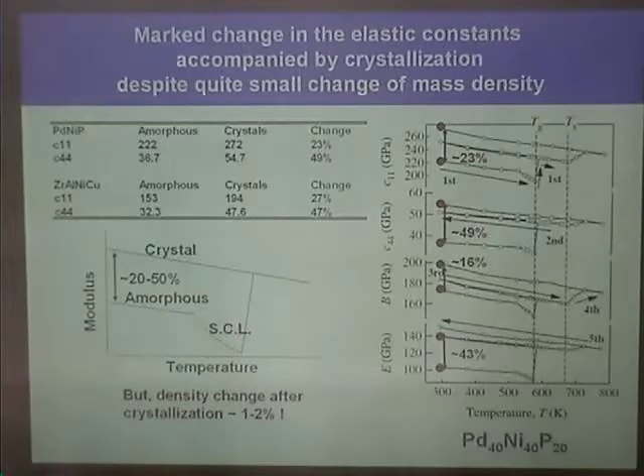That's right. You are assuming that the density change is only 1 or 2%, and therefore that the portion of the structure which changes is also 1 to 2%. That's probably not true. And it's an important question, because what you're trying to do is take this idea and say that there are some local regions that are really inefficiently bonded, and maybe that doesn't follow from this line. I think this is worth thinking about a little more carefully. Yes, no question.